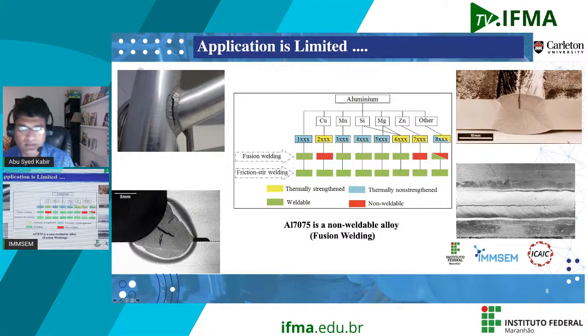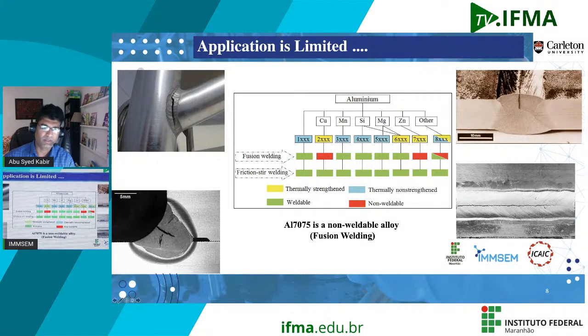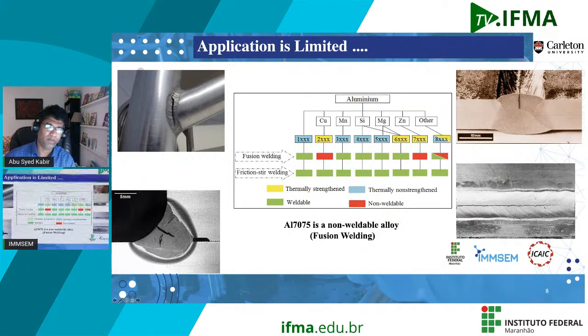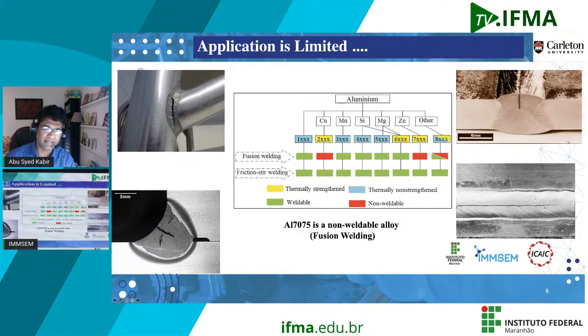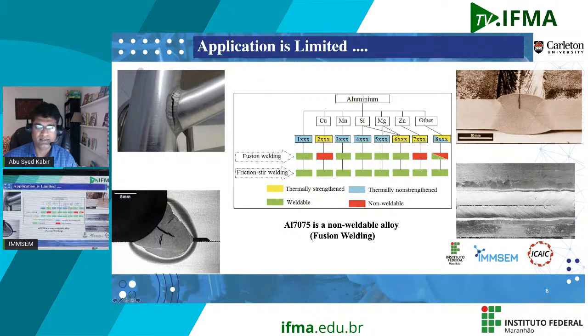And we can see why, because people have tried to fusion weld aluminum 7075 alloy so many times, and every time they came back with this kind of examples, like a lot of cracks here and there. You can see almost all the images. There is a big crack right in the middle. So it's the solidification cracks that we get, and it is the most common in 7075, and that's the only reason that makes the 7075 unweldable in fusion welding.